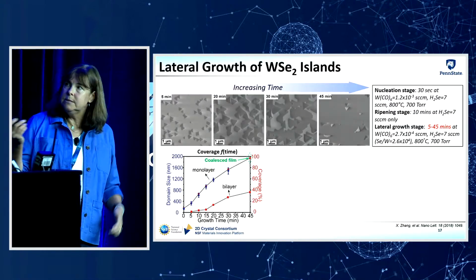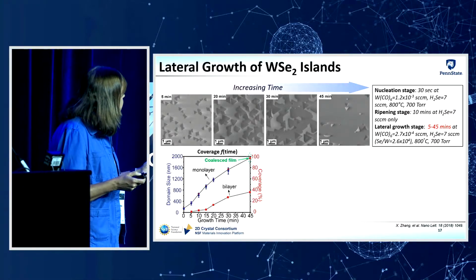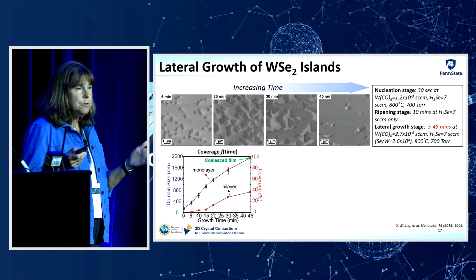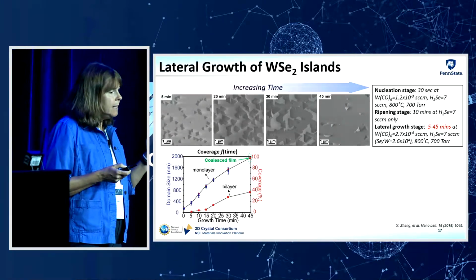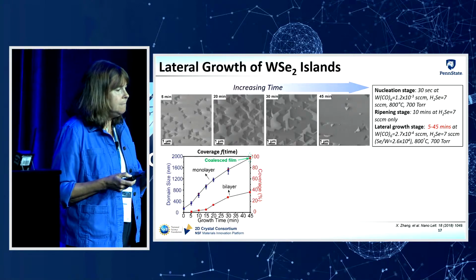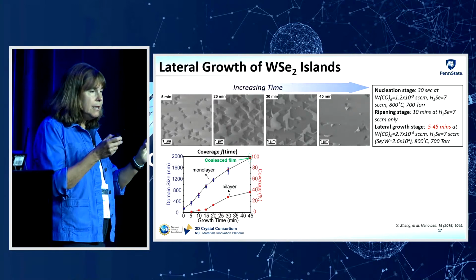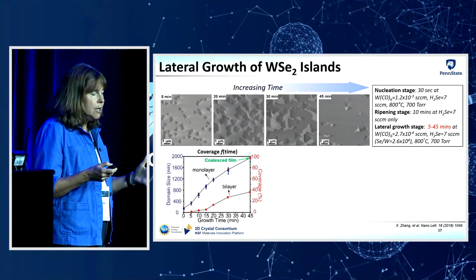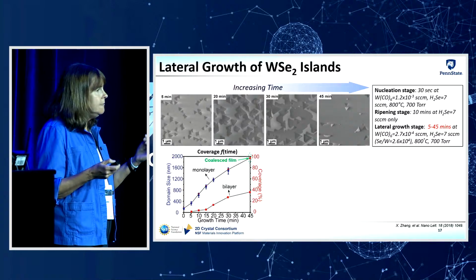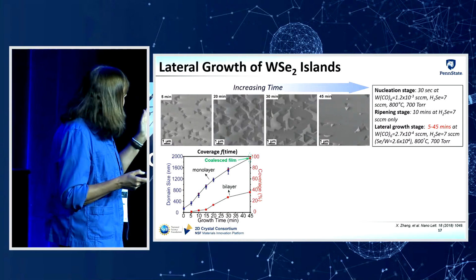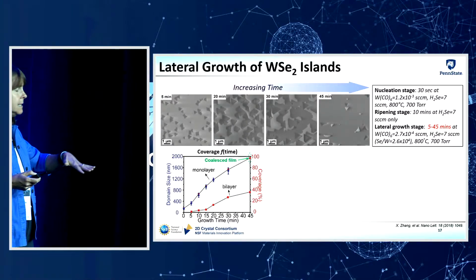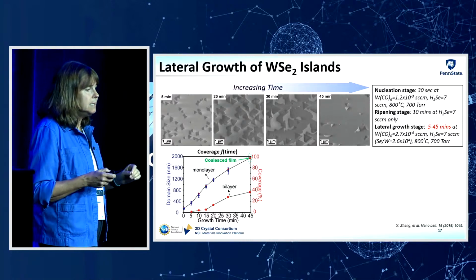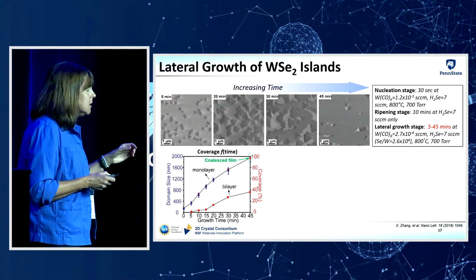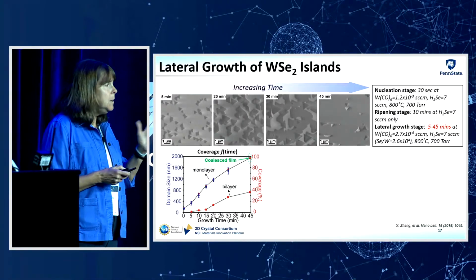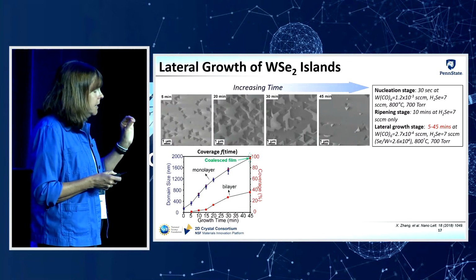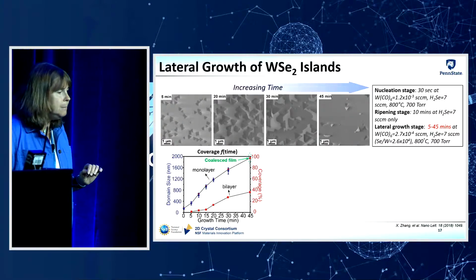So for example, this is an illustration showing how the domains change in size as we vary the lateral growth time. We're increasing the time of that lateral growth step from 5 minutes up to 45 minutes. You can see at 5 minutes, we have these triangular domains. They grow in size, they start to coalesce, and then after about 45 minutes, we have a nearly fully coalesced monolayer. I should point out that the lighter color regions are the underlying sapphire, so the gray regions are the tungsten diselenide. After 45 minutes, we still have a few little holes that haven't filled in, but we also have some bilayers, and those are the darker triangles that appear. You can see that more clearly maybe in the 30-minute image.